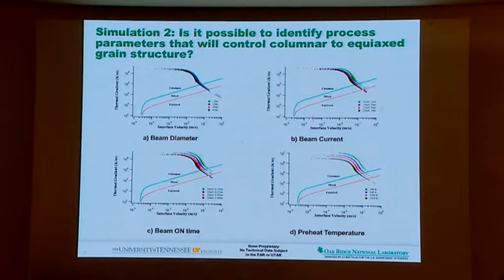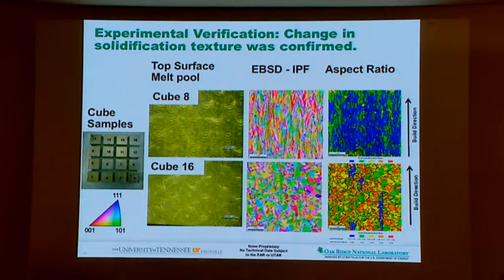So he came up with a new set of processing conditions and implemented them on a cube geometry. He showed that with the cube 8 processing parameter, which is known already, you get this columnar grain structure, this being the build direction. And when he goes into this modified spot melting pattern, you get highly misoriented texture in the same build in different areas. With that, he demonstrated that it is indeed possible to go from a columnar to equiaxed grain structure. Remember, this is the dream of a metallurgist: on demand, in a sample which you are making.